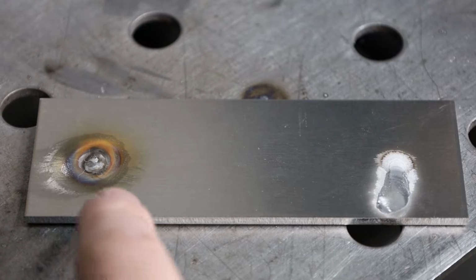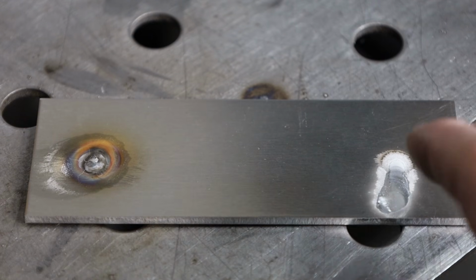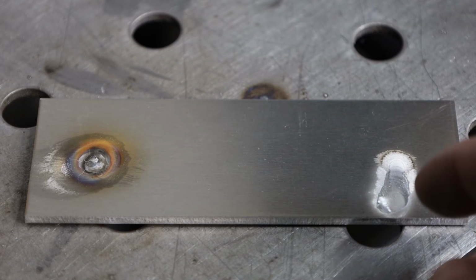So look here where I start making a weld pool with alternating current, and I get a much nicer, cleaner result there. So we'll take a look at these. You can see what it was like just with direct current that put heat into the part versus when I was etching that away. I got a much cleaner, nicer result with the alternating current. And so that's why it's important to weld aluminum with alternating current.